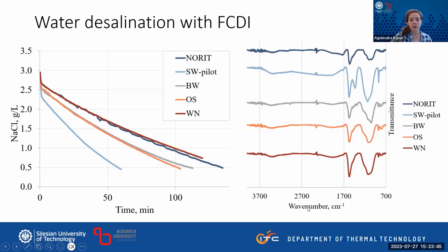And for now, going back to the surface chemistry, we've managed to look at the FTIR spectra of these samples, and the char from the pilot scale gasifier differed from the other ones significantly. It had this peak here at 1400. It might be some sort of resonance stabilized carbon-carbon or carbon-oxygen bonds, either organic or inorganic compounds on the surface of the char.